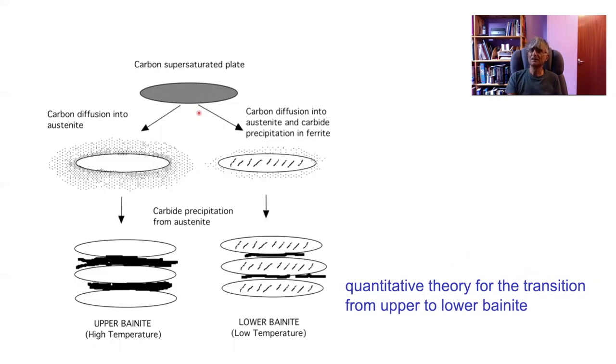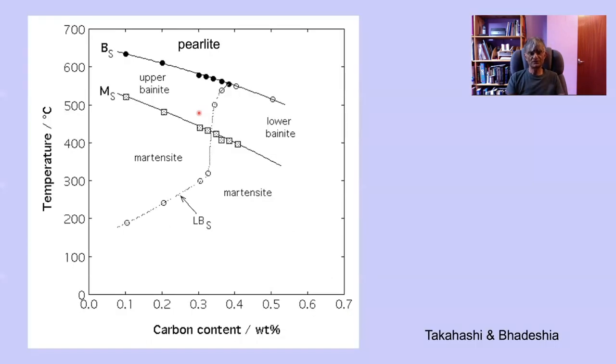And similarly, we can predict the transition from upper bainite to lower bainite, the temperature at which we get upper bainite and the temperature at which lower bainite is generated, using this simple model. And when we first did this, there were some really quite surprising results. So here we are plotting temperature versus carbon concentration. And notice that at low carbon concentrations, isothermal transformation would lead to pearlite here, lead to upper bainite, and then to martensite. So there is no region of lower bainite, because when the carbon concentration is small, the